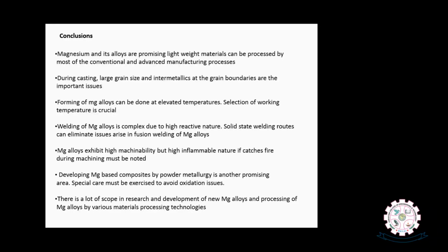And developing magnesium based composites by powder metallurgy is another promising way where we can tailor the composition of magnesium composites by choosing appropriate dispersing phases. However, sintering must be carried out in a protective environment or vacuum to avoid oxidation issues, since magnesium is highly active and can immediately get oxidized. So there is a lot of scope in research and development of new magnesium alloys and composites and processing of magnesium alloys and composites by various material processing technologies.